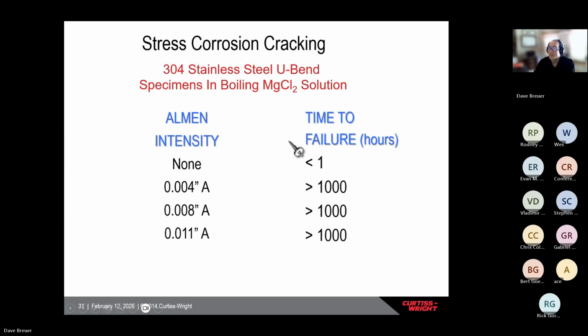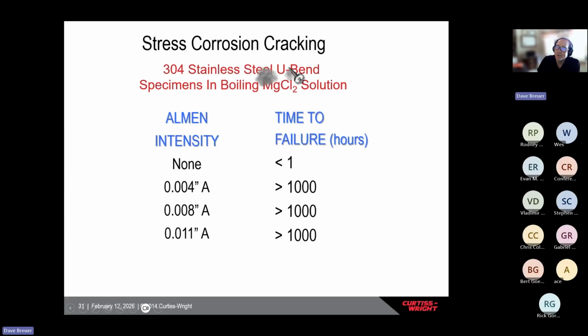This example was a steel U-bend. Imagine a horseshoe shape, and down by the feet of the legs, if you squeeze those legs together, you're stretching the outside of the horseshoe to put a tensile stress on it. This was a susceptible material, 300 series stainless steel, with chlorides in solution. With no shot peening, this fails in less than an hour. With these three different shot peening parameters, it lasts more than 1,000 hours in each case. That's because the shot peening compressive stress replaced the tensile stress that was causing failure.